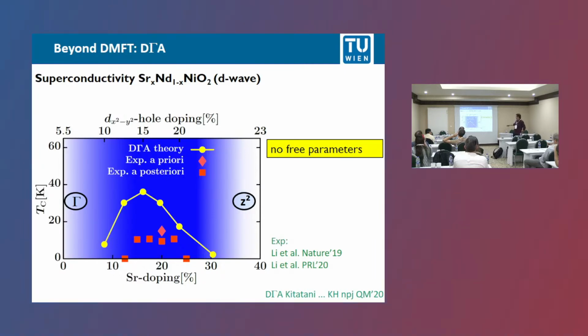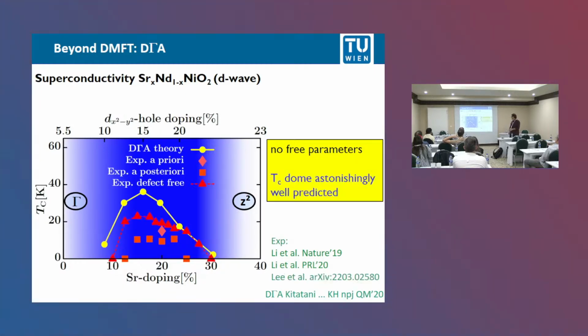Now here there is still a disagreement, as you had at the beginning, which is what you expected, and of course people were asking us, what are you doing wrong here? We don't feed back the superconducting fluctuations to the antiferromagnetic fluctuations. Therefore, we don't get, for example, a Kosterlitz-Thouless transition that overestimates Tc a little bit. So it could have been like that. But then just this year, new experiments with clean films came out, and they gave this Tc. So all we did here is put these films with the strontium doping onto our phase diagram. And that is really in breathtaking agreement.